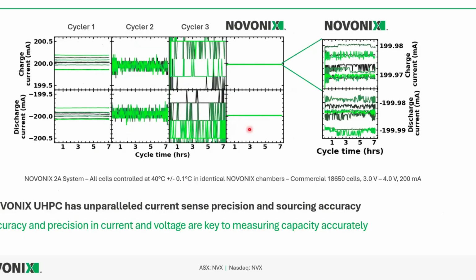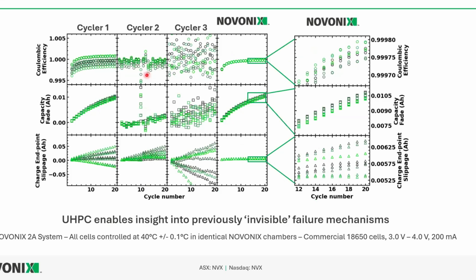The way we do this is, of course, just being very accurate and precise with our measurements. So with these other cyclers here, you can even see things like bit switching in the resolution of some of these 16-bit cyclers. Cycler 1 here has very good resolution, but poor accuracy. And then with Novonix, we have good for both. What this translates to when we think about cycle metrics for Coulombic efficiency, we've already shown this in the other plot, where there's really large spreads between identical cells on these other cyclers, and then very, very consistent results on the UHPC.